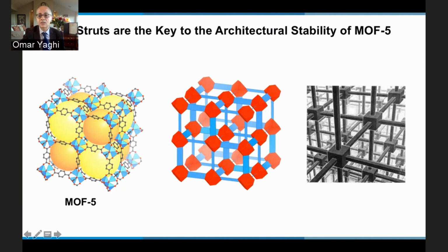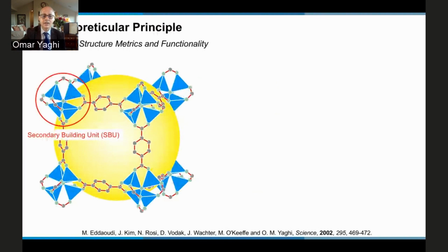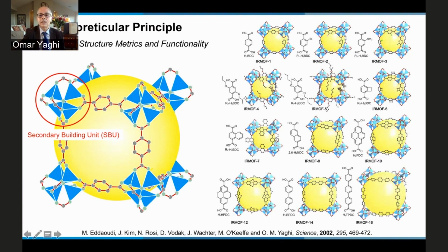And notice here that this is not very much unlike the Escher drawing that I showed you before. The structure is very open, and the nice thing is that if you know the reaction conditions under which to produce this multi-metallic unit, which we call a secondary building unit, then one can add the linker with the desired functionality. And in so doing, you're functionalizing the pores. So you're taking a crystalline material and deliberately fashioning the pores for a specific property and a specific application, as well as expanding the pores to make progressively larger pores so that larger and larger substrates could be manipulated and controlled in the pores.